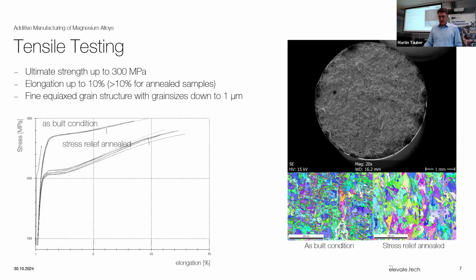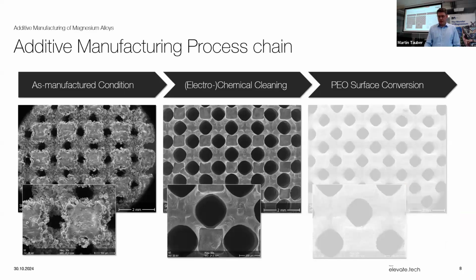Having said that, we can match the necessities of final parts regarding the tensile testing or the tensile strength. So we can reach up to 300 megapascals of tensile strength, and the elongation is over 10%. And we can tailor the material by doing, for example, stress relief annealing or so forth. And you can see below the resulting grain sizes that we get from the different process treatments. Then we come to the next step.